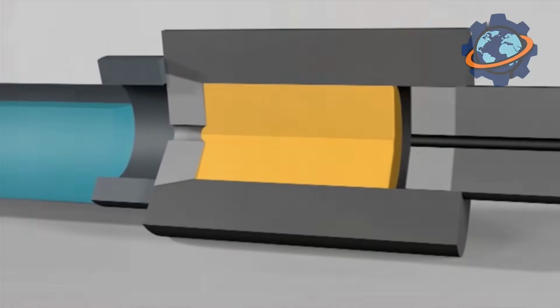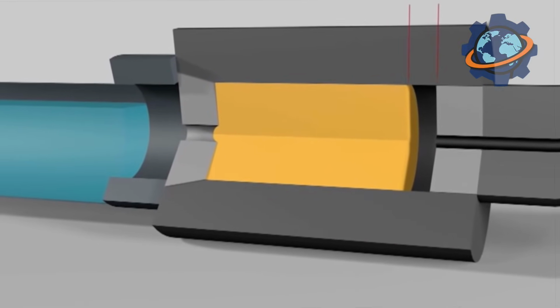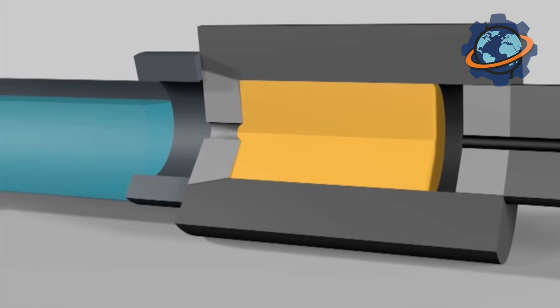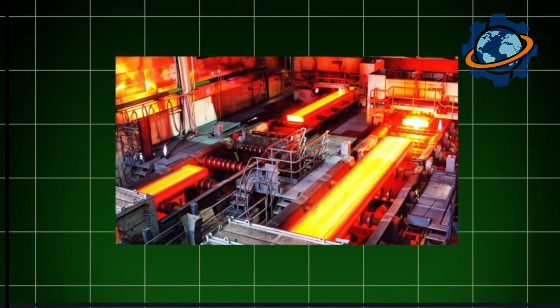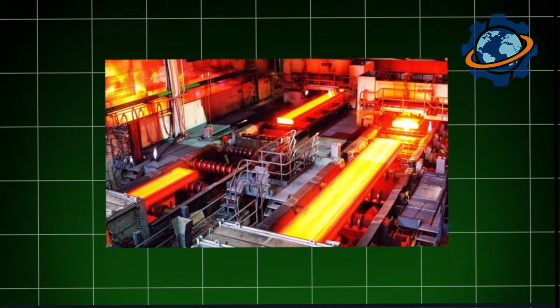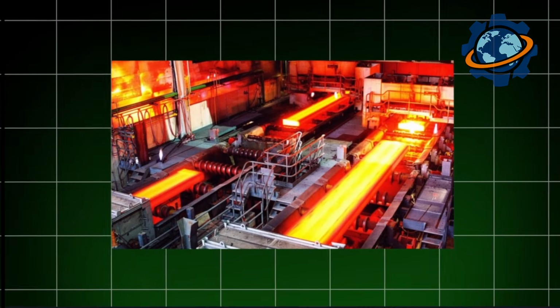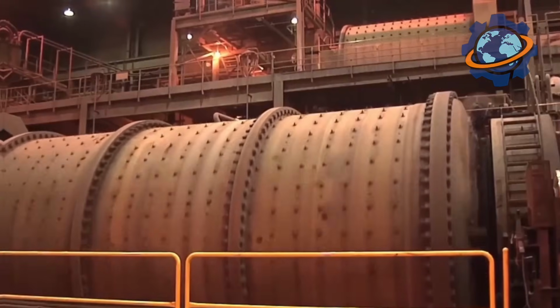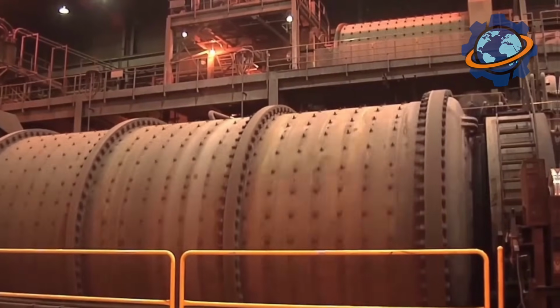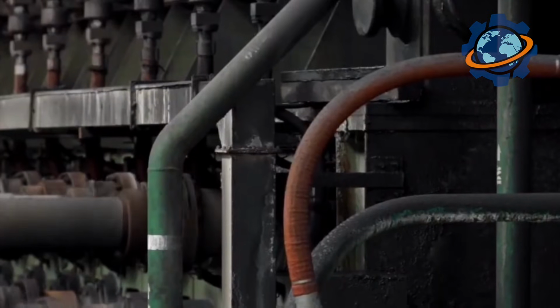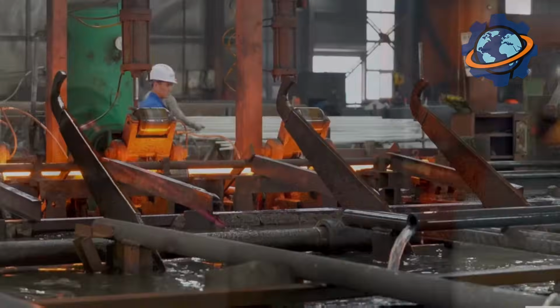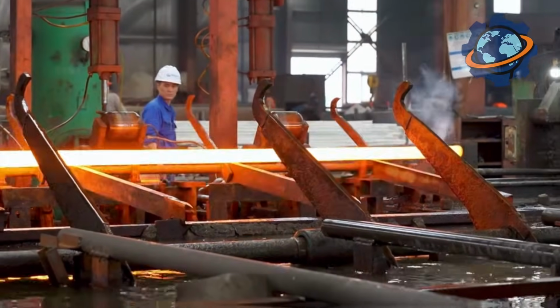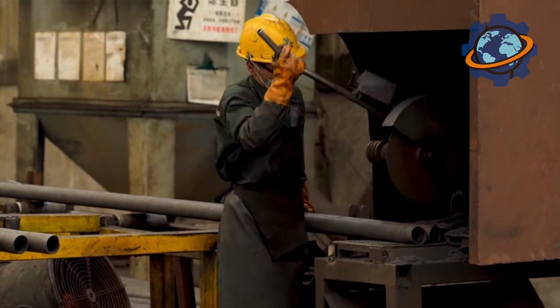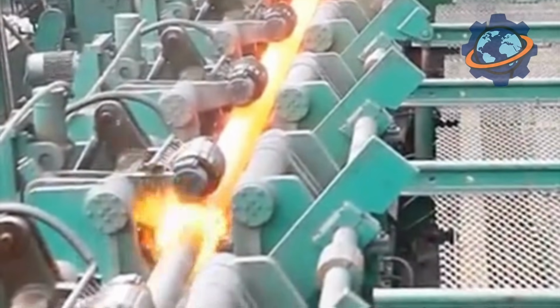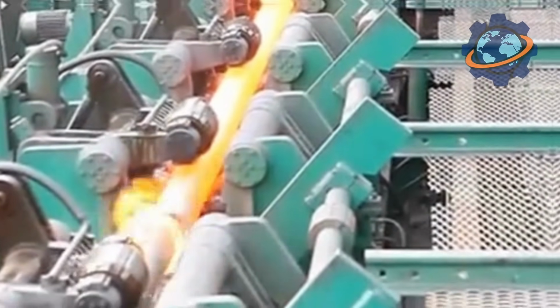The steel screams through at 40 miles per hour, extending like taffy as rollers compress it. Water jets cool rollers constantly. Without cooling, the steel would weld itself to roller surfaces. Scale. Iron oxide forming on surface gets blasted away by high-pressure water, creating permanent rainbow mist in the mill. The noise is beyond hearing protection. Low-frequency vibration felt in bones. One operator describes it. Steel doesn't want to be flat. We convince it otherwise through controlled violence.